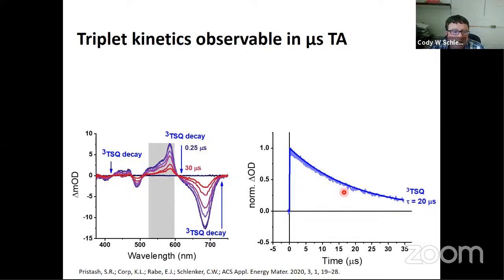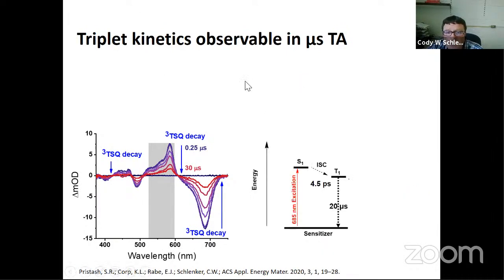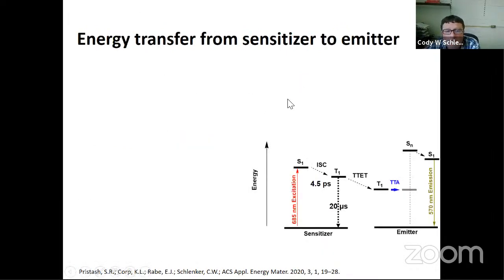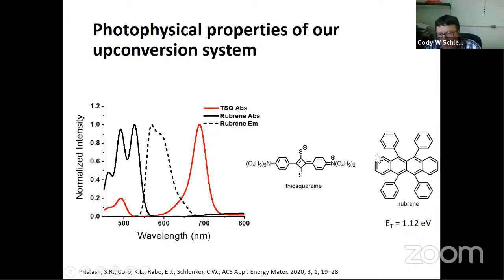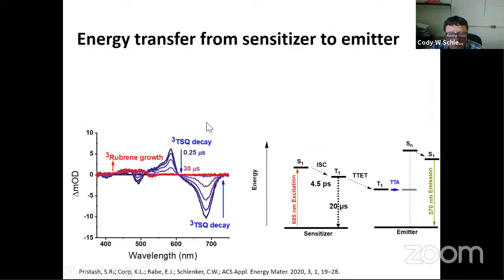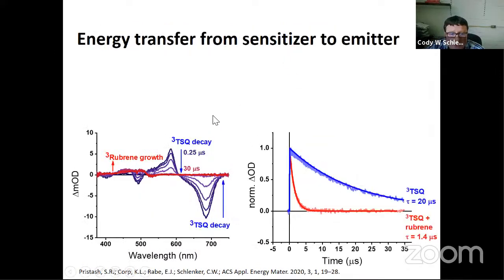We can then add in some emitter molecule to quench that triplet, and in our case we'll use a pretty standard molecule, which is a rubrene molecule. It's a standard molecule for these types of upconversion experiments. It's not really that high performance, but it at least helps us prove the concept of what we're looking at. And so this molecule can quench the triplet energy of our dye molecule.